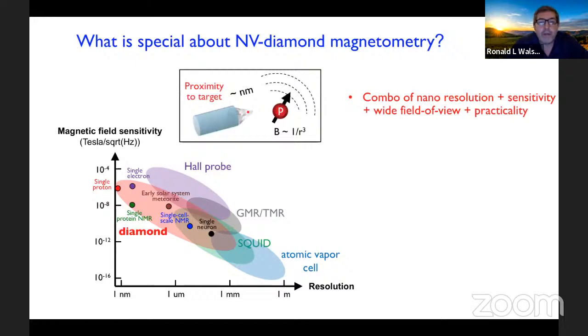Another key feature, though, because the NV exists in this diamond host and can be brought to within a few nanometers of a signal source, like, for example, the NMR signal from one proton, because the strength of signals fall off with separation with some power. The fact that you can bring the sensor into close proximity can boost the signal. If you can get close to a signal source, that signal gets large. And the background noise that might exist in your environment doesn't change. So you can really increase the signal to noise due to proximity. This means often for these sensors, despite their good sensitivity, you don't need to do magnetic shielding.